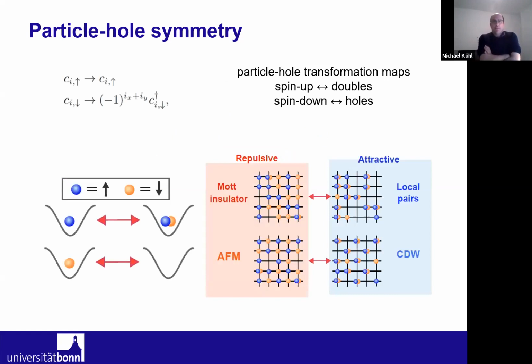Well, there we have to be a little bit more careful because we have to properly account for the spin of the particles. But we can still define a particle hole symmetry operation on this, and that is shown here at the very top. So this particle hole symmetry operation there would be a spin up remains unchanged and a spin down becomes a hole, but with a certain prefactor of the phase, which depends on the lattice index. And what this transformation does, it converts or it maps spin up particles onto doublons and spin down particles onto holes. So it's a spin particle hole symmetry transformation. It is slightly different from the ideal Fermi gas, but in essence, it does the same thing.